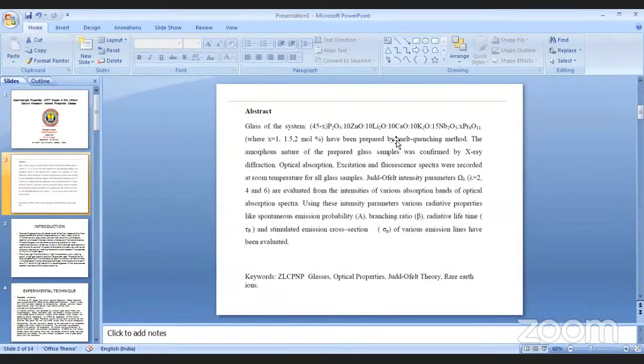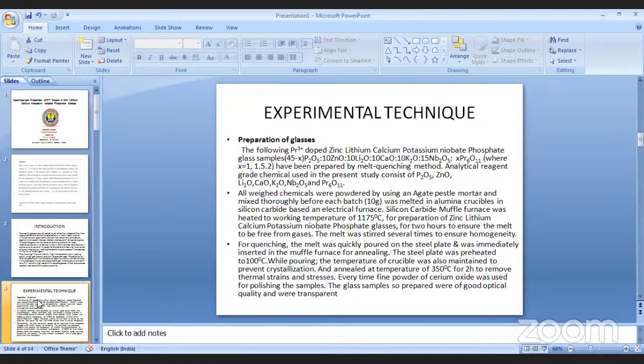The sample was prepared using the melt quenching technique, and the amorphous nature of the prepared glass sample was confirmed by X-ray diffraction. Optical absorption, excitation, and fluorescence spectra were recorded at room temperature, and Judd-Ofelt intensity parameters are also concluded. So I have used the melt quenching technique for the preparation of the glass sample, and the working temperature was 1175 degrees centigrade.